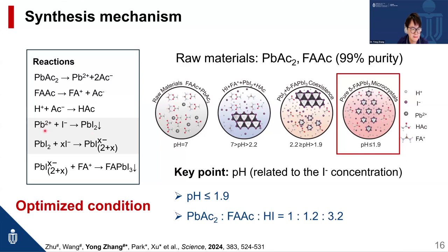In this reaction, controlling the concentration of iodine ion is very important. If the ion concentration is lower, we will form lead iodide as an impurity inside. But if the iodine ion is in excess, then the lead iodide will dissolve to directly form FAPbI3.